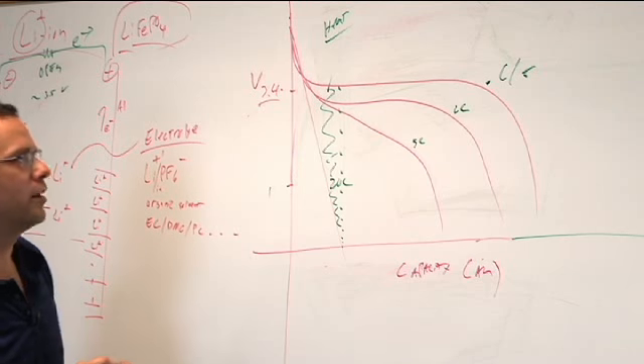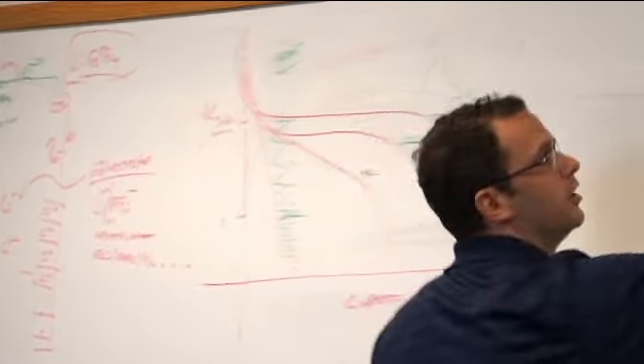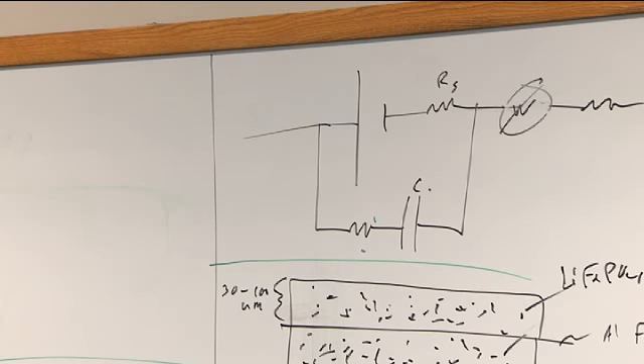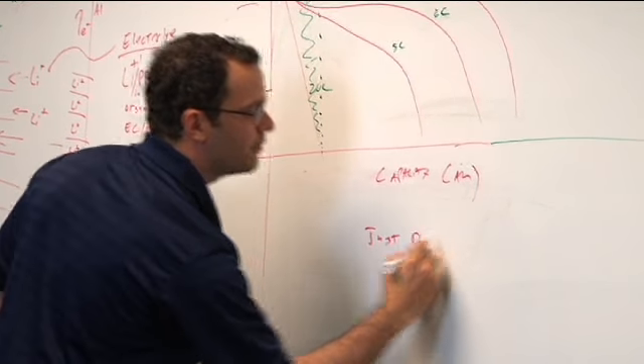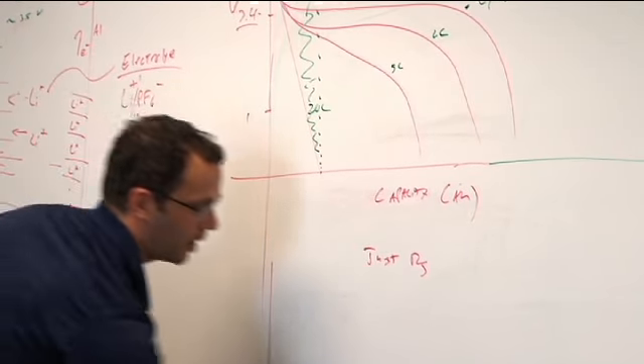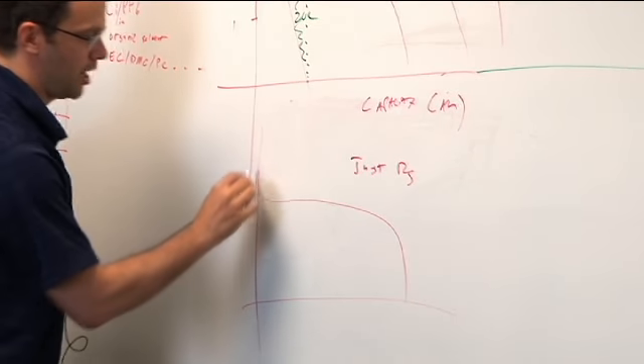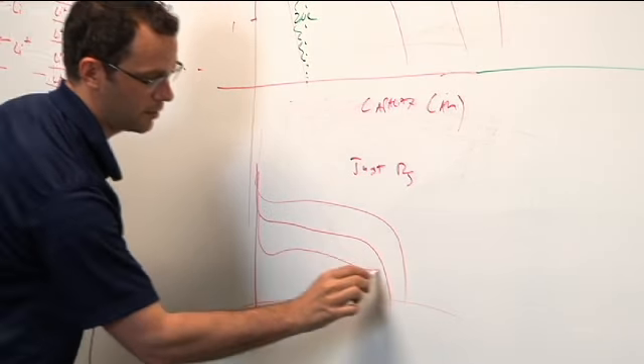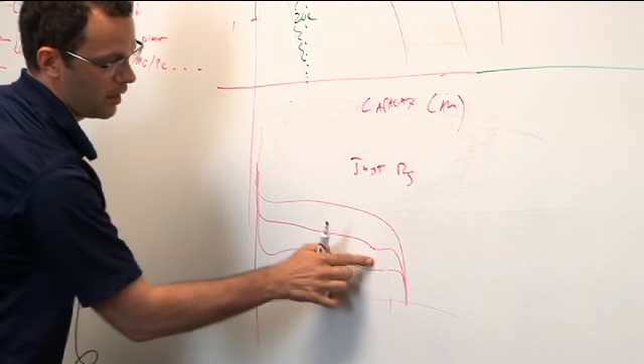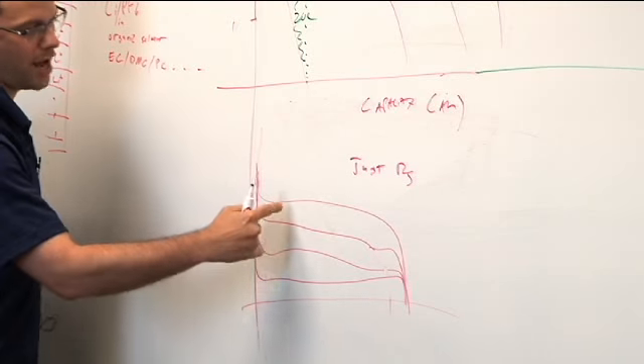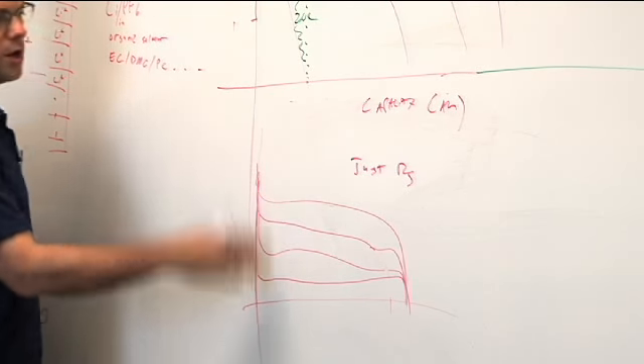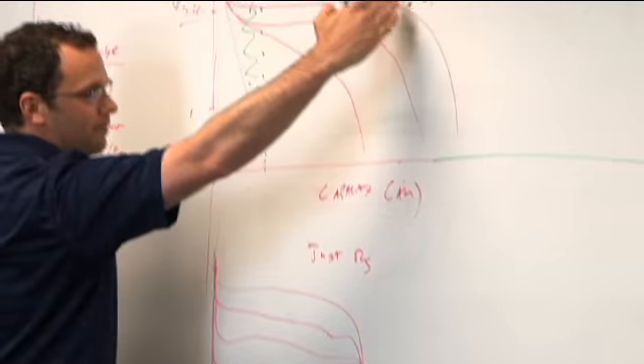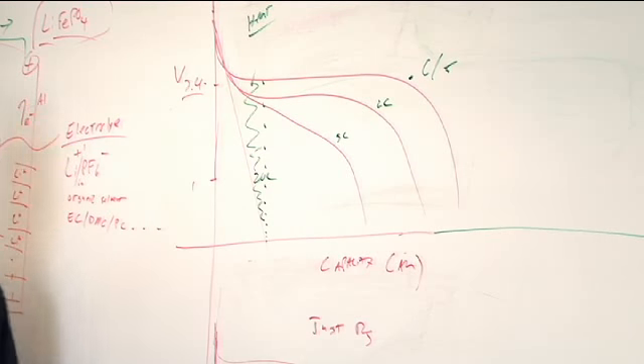But furthermore, there's a couple different things that are happening. I'm going to draw an example down here. If the only problem with these batteries was that they had a series resistance in them, my curves would actually look like this. I would have my equilibrium curve like this, and then my higher current curves would all just go over to here. And then I would have my super high current. All I would have would be this drop, and the difference between this voltage and this voltage would all just be scaled to the ohmic value of this resistor. But that's not what I see. In fact, I see a huge loss in overall capacity as well as a significant voltage drop.